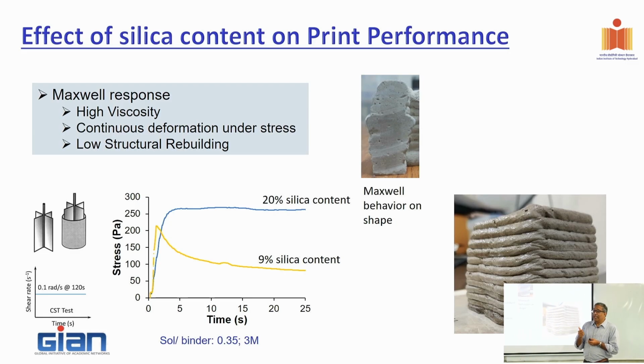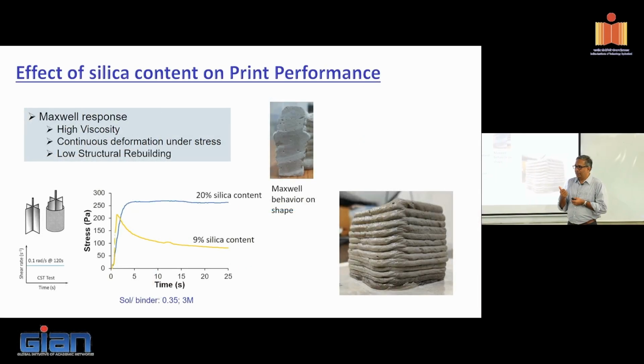But if I don't help it structure, I have a problem, right? And where do I have a problem with structuration? Wherever it starts getting into a Maxwell type behavior is where the structuration becomes a problem. When do I get into a Maxwell type behavior? When I add a lot of silica in it. Why do I need to add silica into the solution? For strength. So it's like a full circle, right?